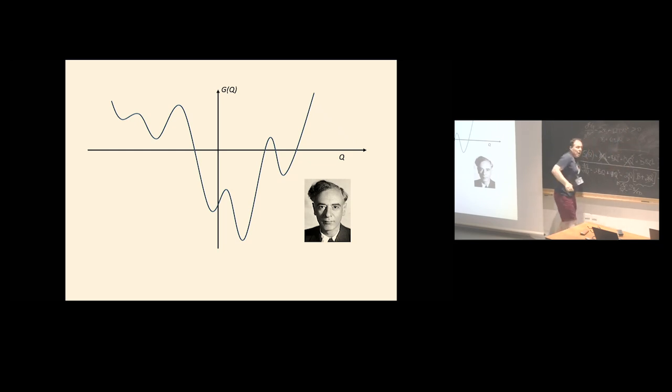All right, we know there are two possible solutions for Q. We've got that already. Q is either equal to 0 for the high temperature, high symmetry phase, or Q is non-zero. It's this, minus B over 2D, for the low temperature, low symmetry phase. So let's talk about high temperature. Q equals 0. Therefore, B plus 0 must be greater than 0. And so B must be greater than 0. Okay, so B is the prefactor in front of Q squared.